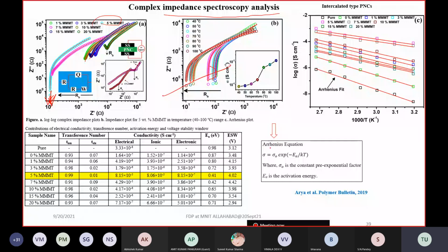It has also been done with temperature in order to find its activation energy. Activation energy is the energy by which you can estimate how easily lithium ions are going to move from one side to another side. So for that reason, this activation energy is to be calculated. Ionic conductivity is also calculated on the basis of transport number analysis that we'll see in the next graph. But the activation energy, as you see, is also calculated using the Arrhenius equation fitting in this graph.